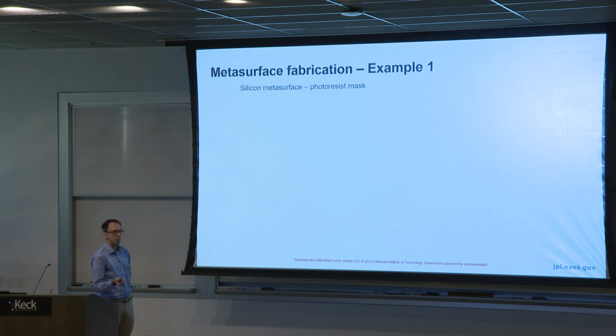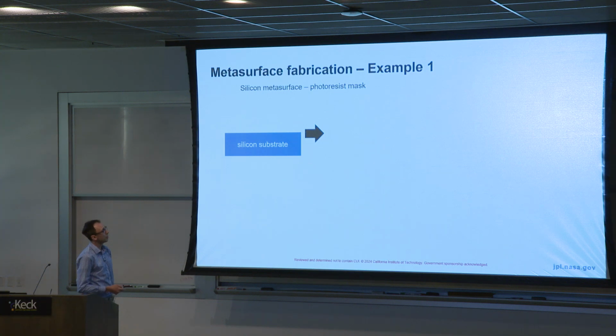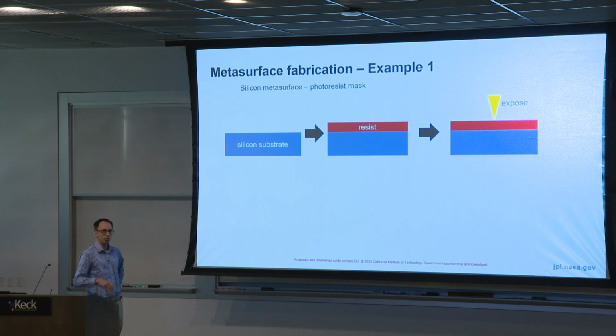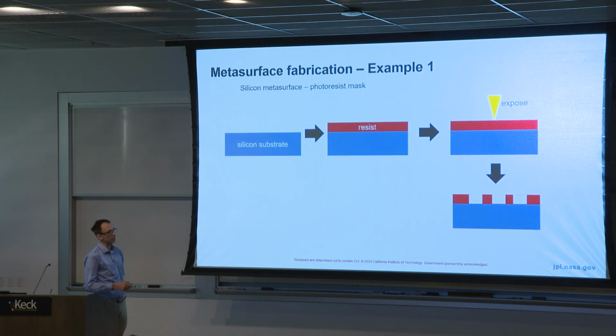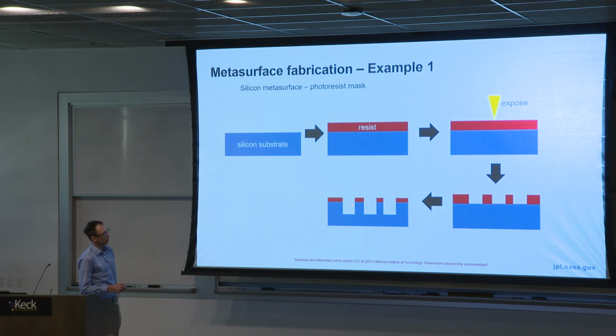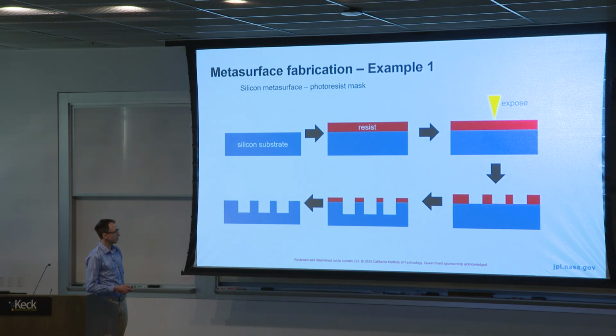Maybe okay. So the most straightforward thing to do is to make a pattern. Let's call it a metasurface, but it could go for any pattern. So you make a silicon metasurface using a resist mask, maybe even for electron beam lithography. You start with your silicon substrate, you go out and you buy this. You've bought resist, or you find it in your clean room, and you spin coat it on. So far everything is pretty easy. Now you have your computer generated pattern, and you expose this pattern using your E-beam or your stepper system or whatever. You put it into the developer, and you develop for as long as you need to make sure that you have your pattern. So now you have ended up with your metasurface pattern. It's just not in the substrate, in the material that you want; you have it in your resist. Now you take your favorite anisotropic etch that you magically found, and you do a perfect job of transferring this into the substrate below, so you create these well-defined, vertical pillars. Then you remove your resist in the end, ideally without damaging any of the delicate features that you made.